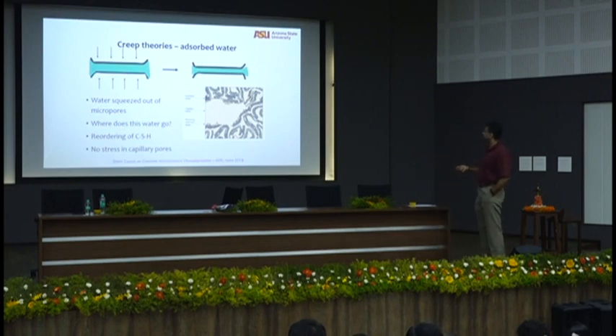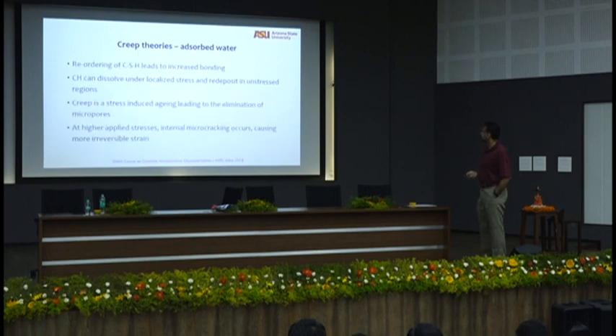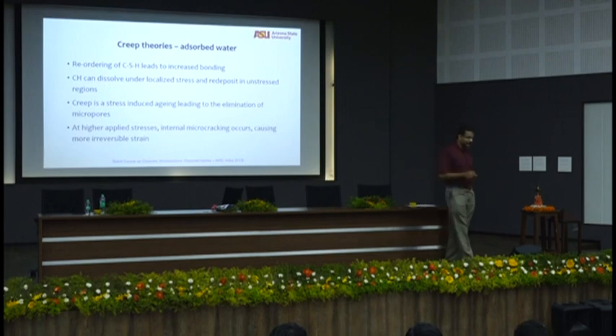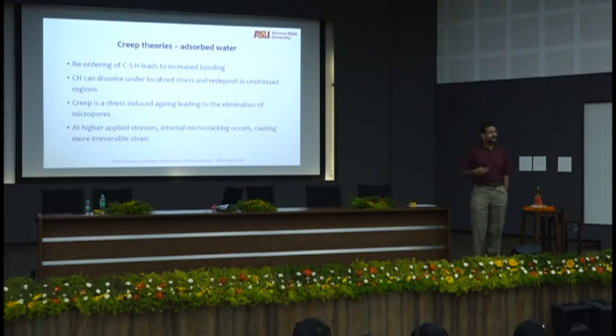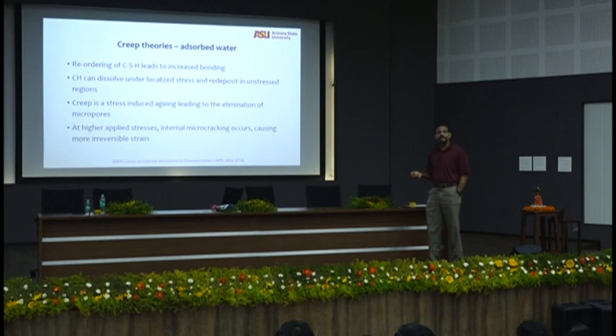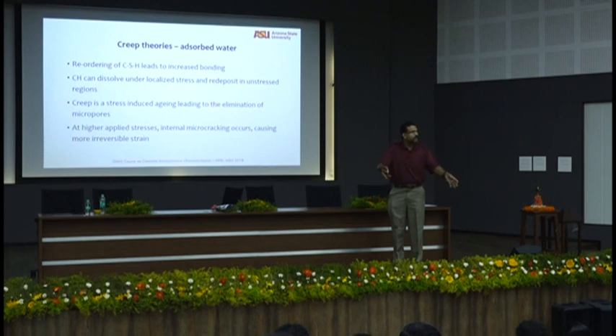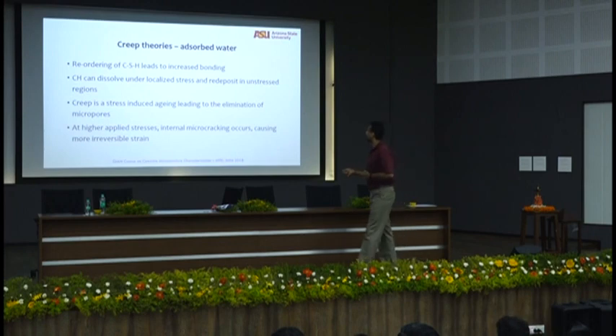Water squeezed out of micropores. Where does this water go? Reordering of CSH. Like I told you earlier, there is no stress in capillary pores at all, so you just have reordering of CSH. Reordering of CSH sometimes leads to increased bonding, and under high stress, calcium hydroxide can dissolve. Have you heard of stress corrosion cracking? Corrosion can happen under stress. Similarly, calcium hydroxide can dissolve under localized stress. When you have very high stress in this crystal, the crystal wants to dissolve to release that stress. So calcium hydroxide dissolves, and then it will redeposit.